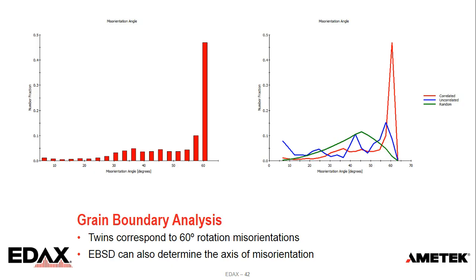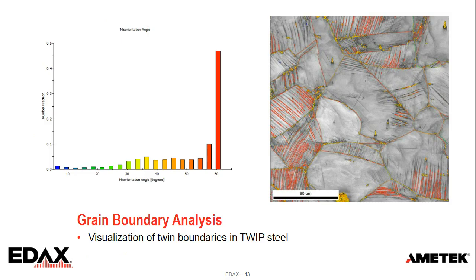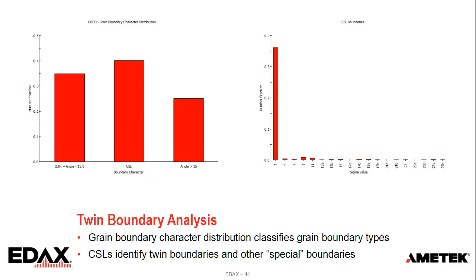character distribution. And again, like we did previously, we can highlight these. So with color highlighting, we see the twin boundaries come out in red, sort of as we'd expect. And we can characterize all the boundaries in there. So the plot here on the left shows our GBCD, where we have low angle boundaries, CSL boundaries, and high angle boundaries, and we can get an idea of which is which.